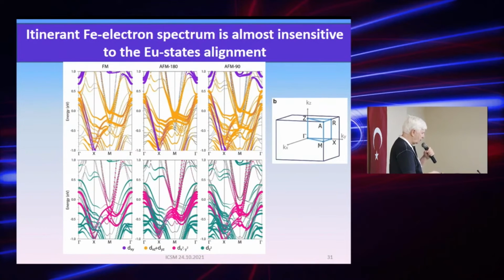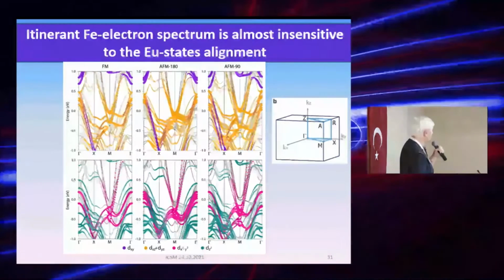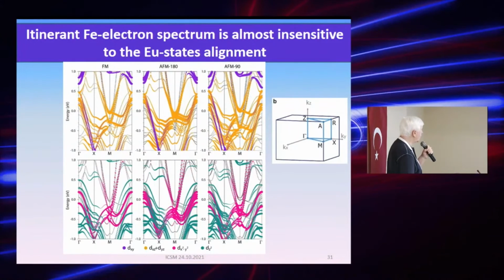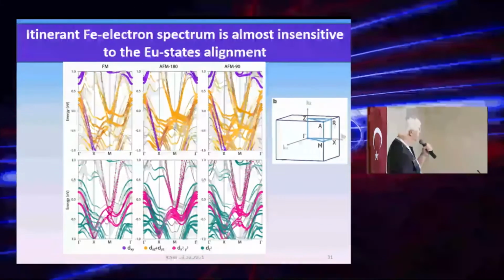The result, which is compared for these 3, is the ground state energy. It's almost the same, but still it's slightly lower for the AFM 90, so that the preferable rotation angle between the europium planes is 90 degrees, according to this DFT calculation. But as you well know, the DFT calculation has quite a large uncertainty.